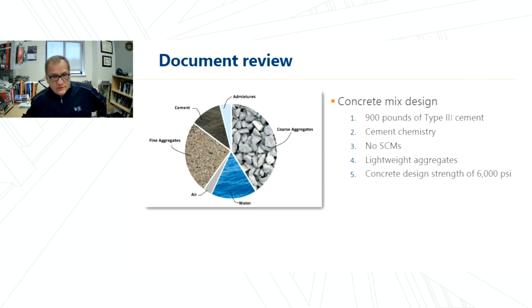So, circling back a little bit to our investigative process, we did do document review. In this particular case, we took a look at the mix design that was used to fabricate all of the double T's, and that included 900 pounds of type 3 cement. Why is that significant? It's significant for a couple reasons. One is that 900 pounds is a lot of cement in a mix design. In addition, the type 3 cement is a very fine cement, meaning both of those would generate a lot of heat during the early ages of the concrete.